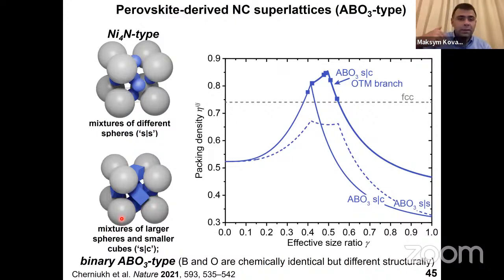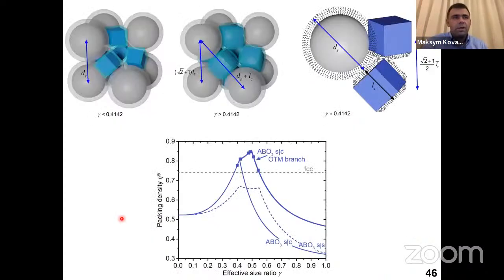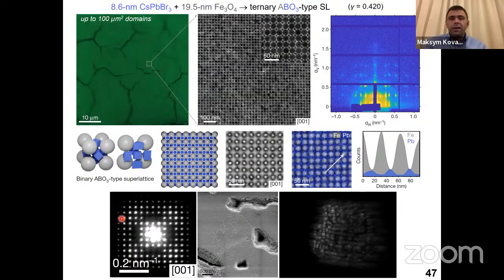and this lattice is very much favored compared to the phase separation. So you end up with a very nice, very clean yield of this structure. It outcompetes phase separation by far.